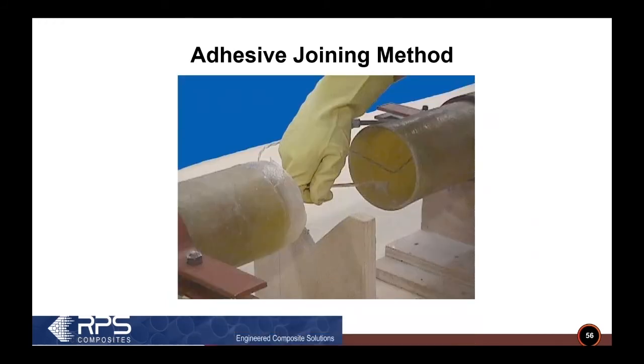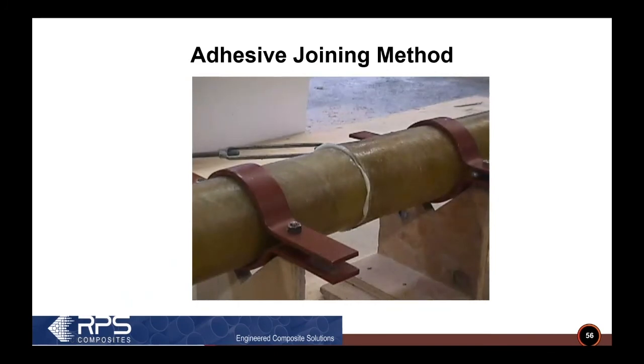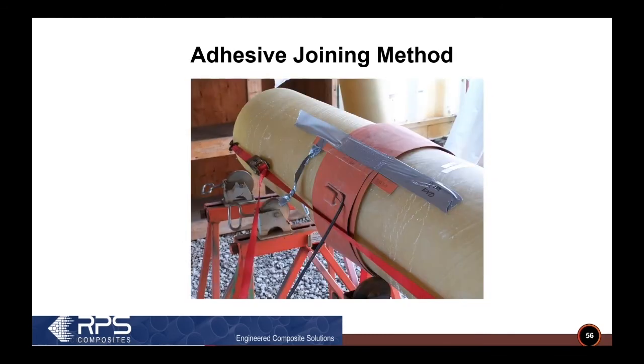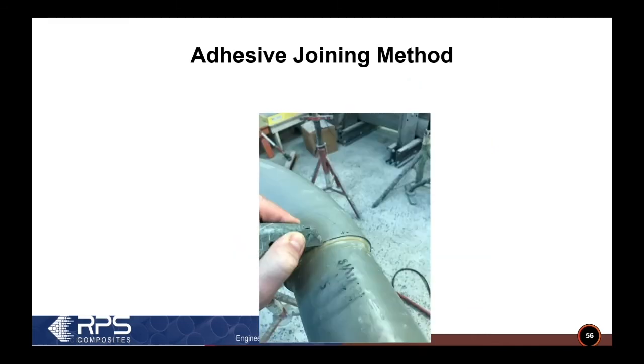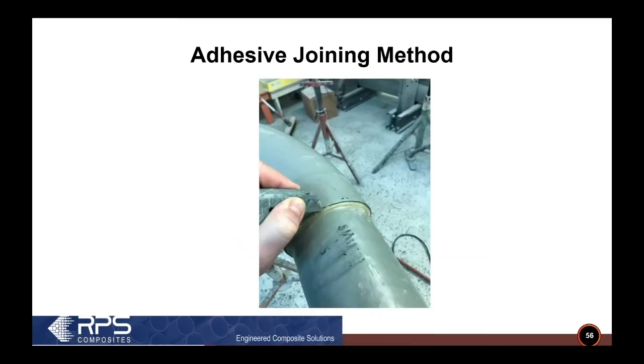You put adhesive on both the female and male ends. You bring the 2 pieces together, and we show some clamps here because you actually have to hold it together so it doesn't come apart and you don't draw air into the joint. And then because the joint creates a very thin glue line, or thin adhesive line, we actually cure the joint with a heating blanket. And the finished joint is going to be as hard as the original piece of piping.